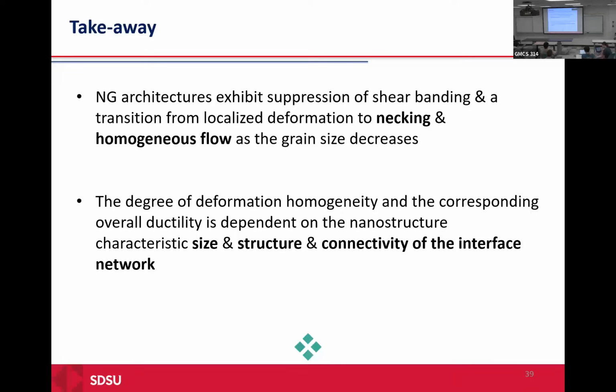Then by working on the grain size and the network of these grain boundaries, or by making a composite of those materials, it's possible to tune the behavior of the total metallic glass, hopefully getting some plasticity and also a good strength of those materials.